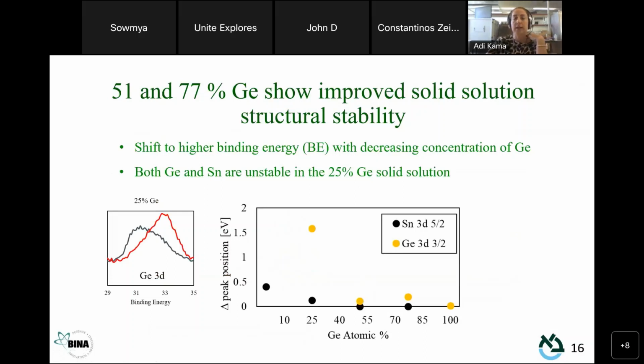Before we implemented it in a solar cell, we wanted to understand a little bit more about the stability of those materials and how they affect each other. And we performed XPS measurements, which are surface sensitive measurements, on 5 fresh samples and on 5 samples that were left in the nitrogen glove box for a week. And we wanted to see if we have a shift of the binding energy that will indicate a change in the oxidation state. In this plot, we have the change of the shift in binding energy.